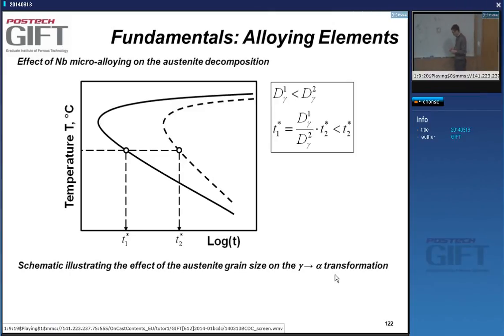Now, what's important here is this. When I have large grains, these guys don't look like these. Here, there's no nucleation, nothing is happening here. If the grain size is small, and I look at the same distance, the same unit, I will also have a grain boundary in this unit, and this one will also transform, the same way. Two units, not more. There's no magic. It's just that this one doesn't do anything. Whereas here, the nucleation rate being the same, I still get faster kinetics, because of the grain size.